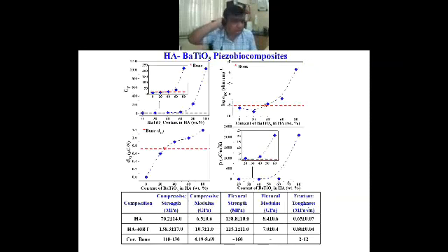And when we measured the mechanical properties, particularly I would like to draw your attention to d33, the piezoelectric strain coefficient. The bone piezoelectric strain coefficient, as I said before, is 0.7 picocoulomb per Newton. And we found that somewhere between 20 to 40% barium titanate content, we could achieve the bone piezoelectric properties in the synthetic biomaterials.